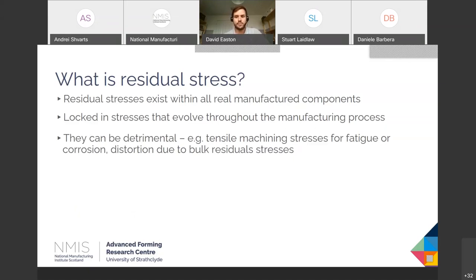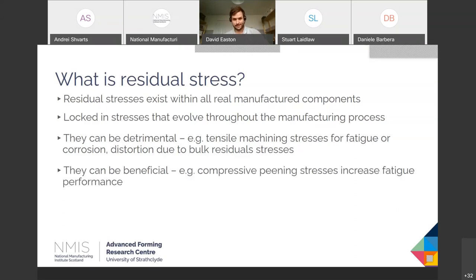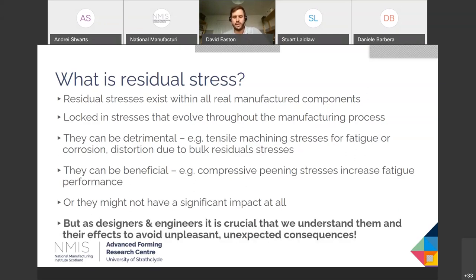They can be detrimental. For example, tensile machining stresses can negatively affect fatigue or corrosion. We can get distortion coming in from residual stress. They can also be beneficial. For years, compressive residual stresses have been intentionally induced using peening because we get better fatigue performance. And in some situations, they might not have any significant impact at all. But what is important is that we as designers and engineers understand what the residual stresses are, how they are in our material, and what can happen if we don't take account of them.